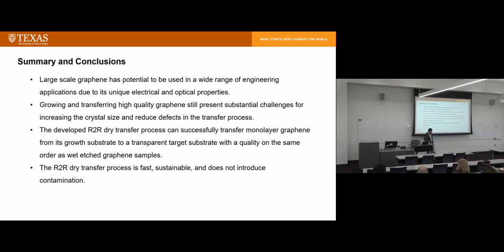So there are efforts in Korea and in other parts of the world, they're growing single crystal graphene. So if you can grow single crystal graphene, all the problems in the transfer process will be gone because single crystal graphene is strong, right? No matter how you peel it, it's going to be peeled. It's not going to crack. And there's no defects in it. So my former colleague, Rani Ruoff, in their group is trying to grow single crystal graphene, but I think the largest crystal size is still under a millimeter. You still have those defects in graphene.